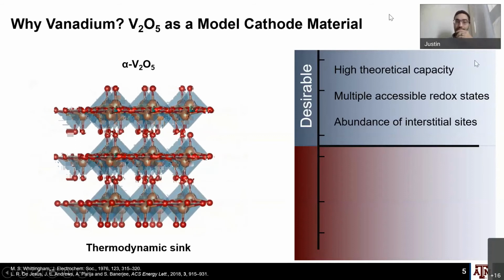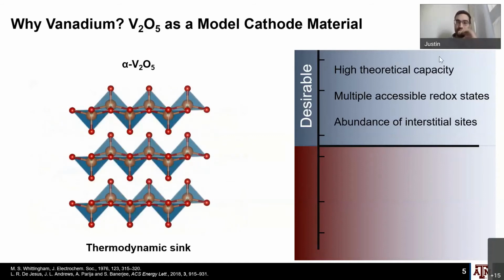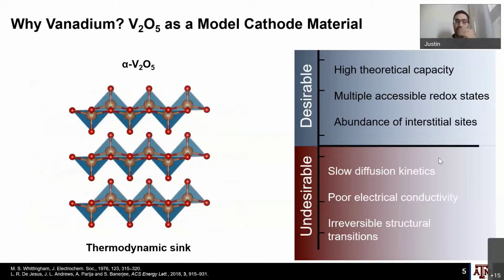It has a lot of desirable properties in terms of just the crystal structure and the composition, including multiple accessible redox states, vanadium 5 to vanadium 4 to vanadium 3 potentially. And the problem, which was realized early on, is that there's really sluggish diffusion kinetics. The material has a really poor electrical conductivity. And then as we lithiate this material, there's also a series of irreversible structural transitions that really prevent us from accessing a lot of the potential energy storage that it has as we pump lithium into this.